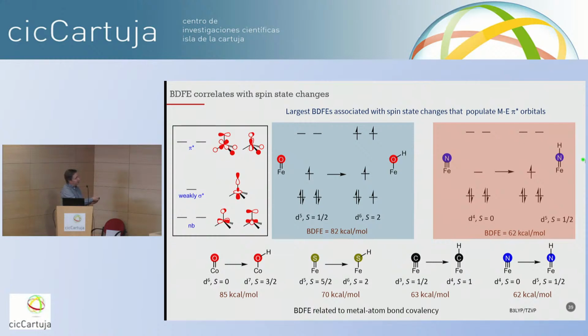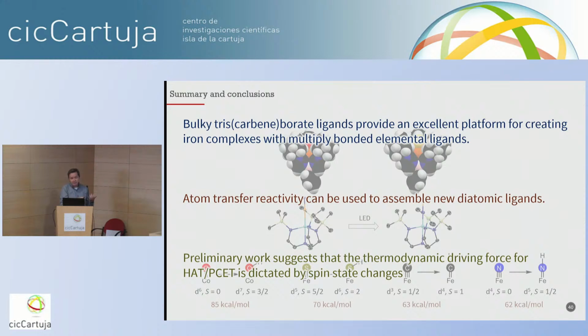And our working hypothesis is that this is related to the covalency of the metal ligand multiple bond. So the more covalent it is, the weaker the resulting element H bond that's formed. Okay, so just to wrap everything up, hopefully one thing you got out of this talk is that these bulky tris carbene ligands are a really great platform for making these metal ligand multiple bonds, particularly with elemental ligands that don't provide much steric protection by themselves. We can use atom transfer chemistry to assemble new ligands, and then we're looking at how thermodynamic driving force is related to the bonding properties of these complexes, particularly their covalency, which is going to affect spin state changes.